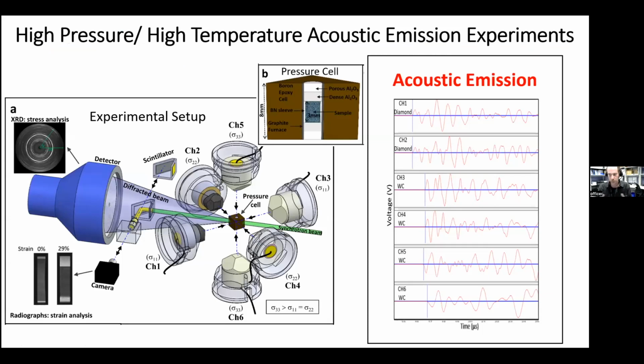So we run similar types of experiments. So basically you have a pressure cell at the center, you have 6 anvils surrounding it, and at the center of your pressure cell, you have a sample, and typically about 3 millimeters long, 2 millimeters wide. Here's one of them. I'm assuming you can't see that. That's kind of the point. They're very small.